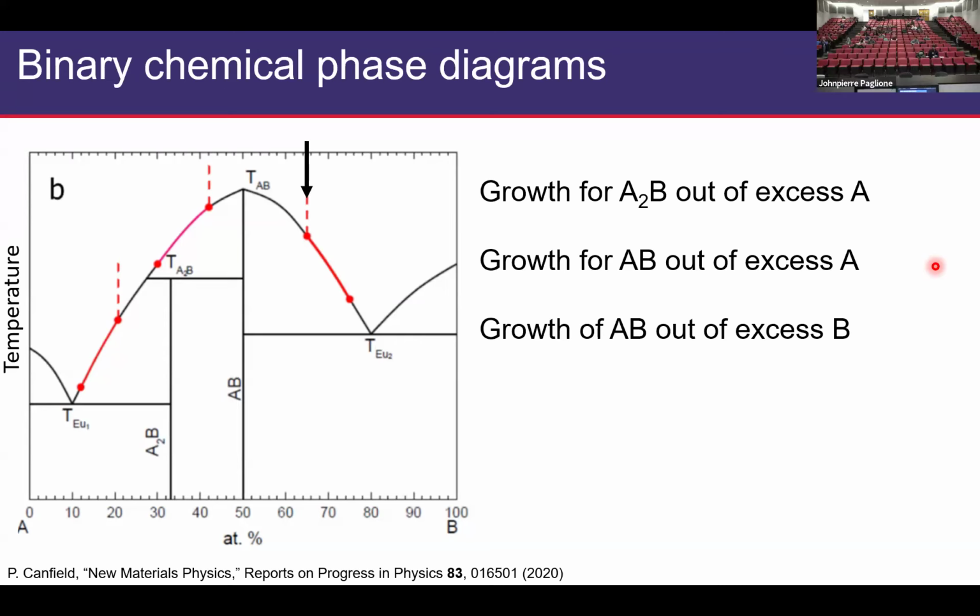I think this assumes you follow the liquidus line slowly enough. That's right. If you go quickly through that liquidus line, you're going to wind up not letting AB come out in a clean manner, and you really will end up with just a messy result.